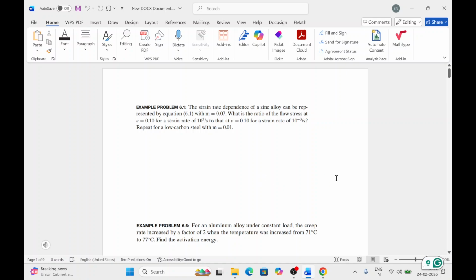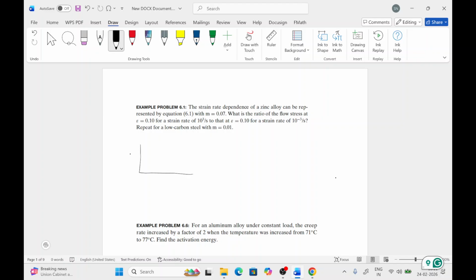So you see in the uniaxial tensile test the stress strain curve looks like this, sigma versus epsilon. Up to this point is the yield strength, and this point is the tensile strength. Between these 2 points, the behavior of the material is different from the behavior before the yield strength. This is the plastic region and this is elastic. In the plastic region we follow strain hardening behavior: as the material deforms, it gets strain hardened due to the formation of dislocations.